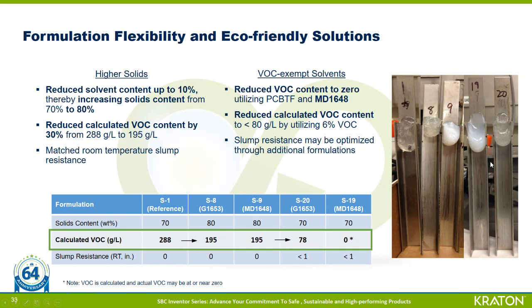One may be able to reformulate around this and increase the slump resistance back up. So for instance, we could have possibly increased the solids content back up, say 3 to 5%. So still keep a manageable viscosity, but then improve your slump resistance back to the reference sample. It should also be noted that the VOC content may be measured or calculated differently for the different regions or market segments, and that should be taken into account for your situation accordingly.